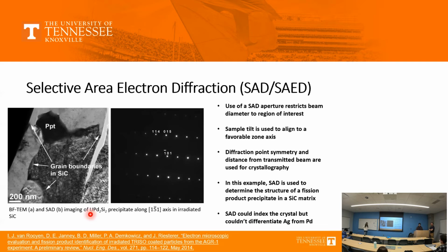Yeah. And another way to think about it is, in this foil, you may have a 50 nanometer thick foil, but if your precipitate is only 10 nanometers within that, then 80% of that vertical cross section is matrix and not precipitate.